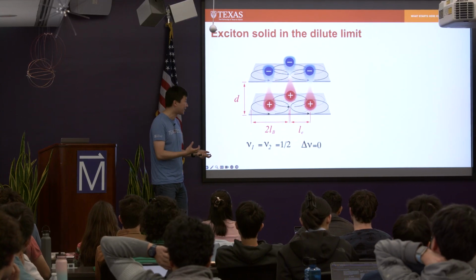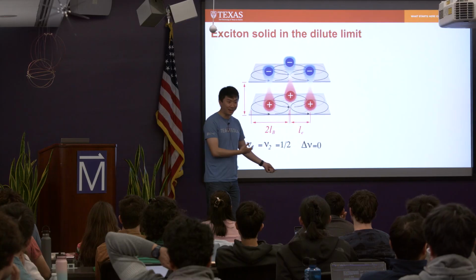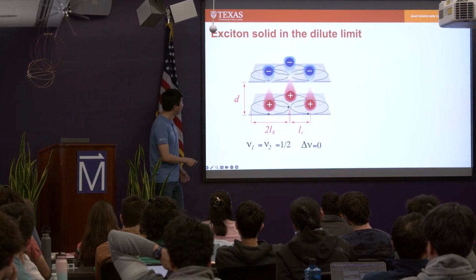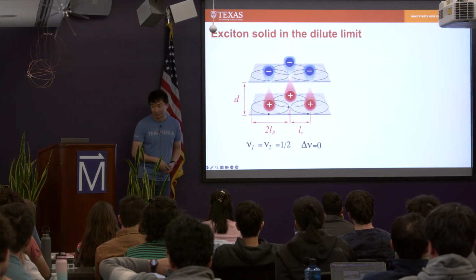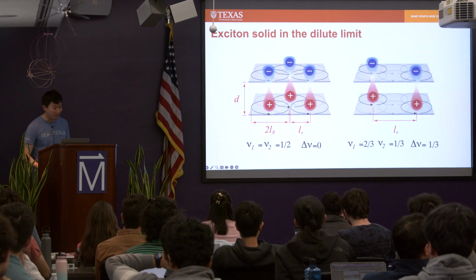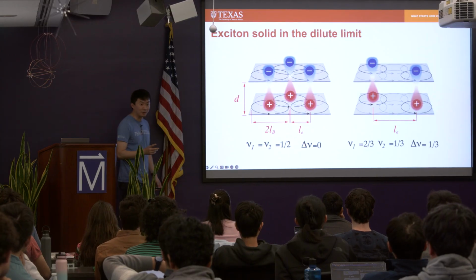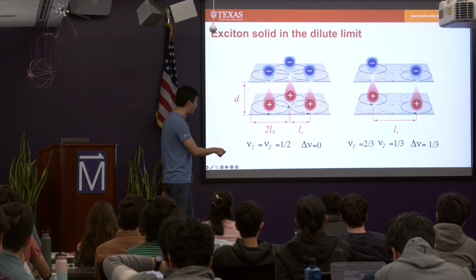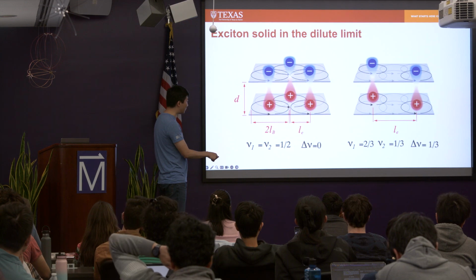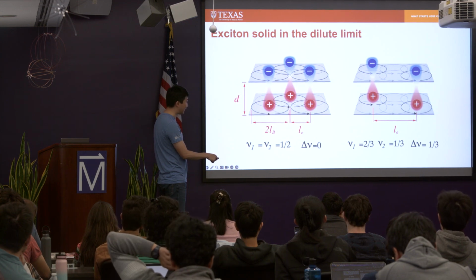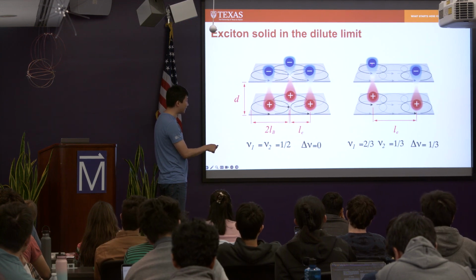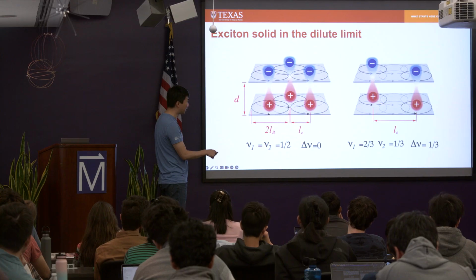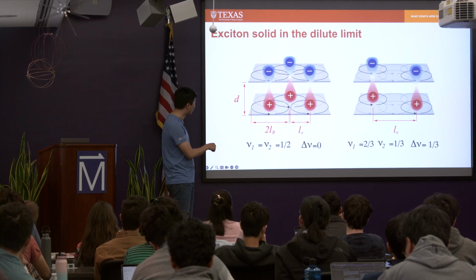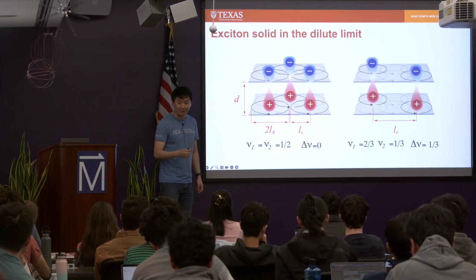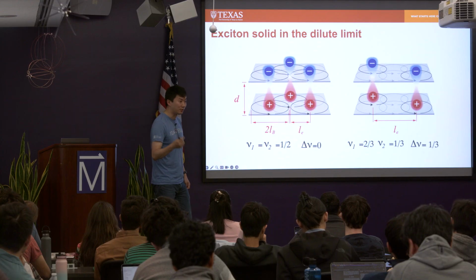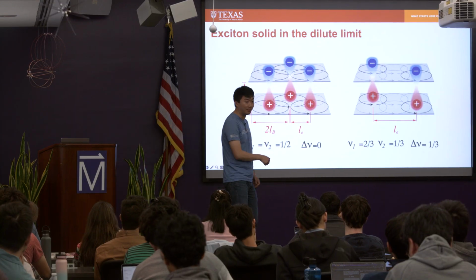The ratio is always the same. Once we come to that conclusion, we realize that actually there is something that we can do to go to the dilute limit. And all we need to do is to create an imbalance between the two layers, right? So this is schematic. I'm plotting what happens when one layer is at 2/3 filling, the other layer is at 1/3 filling, right? In this case, you have 2 excitons, the interlayer separation becomes much larger compared to this case, right? You can push this to the more extreme regime that you can get to really dilute limit, right?